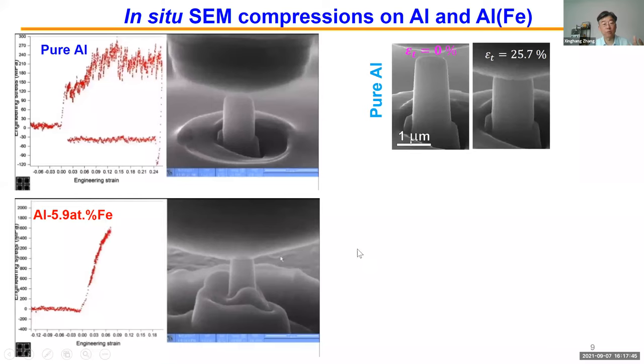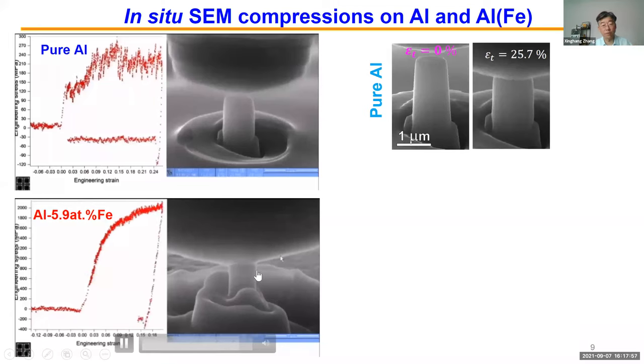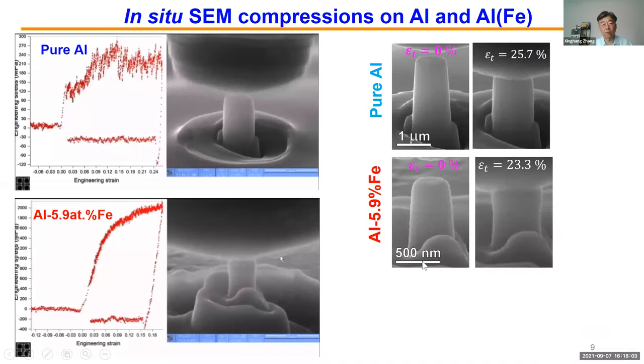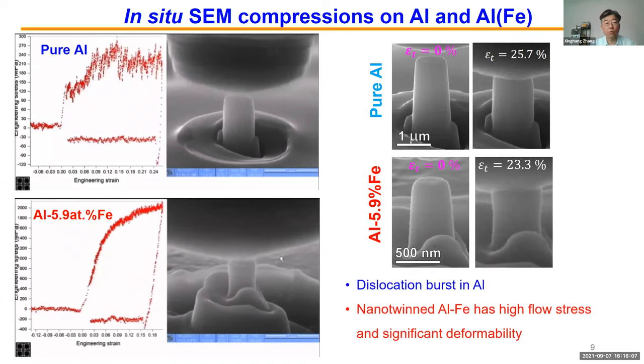atomic percent of iron using sputtering, you find the flow stress is a lot higher. This is the engineering stress from the curve. Now it's already exceeding 1.5 GPa in this alloy. Plus, you can see the pillars have classical bulging on the top, and there's no shear band, no fracture generally. So this is encouraging because we see substantial plasticity in this aluminum iron.